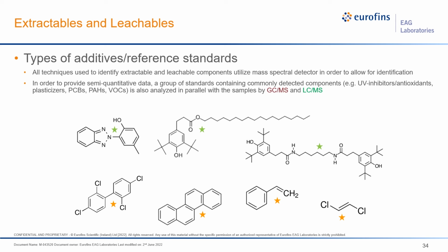In terms of what we're detecting and what we run alongside our samples, again, we use a mass spectral based technique for all the identifications, otherwise identification can be very difficult. We also analyze groups of reference standards alongside our samples so we can provide semi-quantitative data for materials or components that we detect. These can include, again, UV inhibitors or antioxidants, plasticizers, polychlorinated biphenyls, polyaromatic hydrocarbons, and volatile organic compounds.